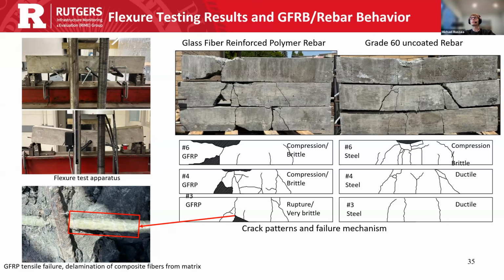And we can compare this to steel, where an over-reinforced section crushes at the top, as you know, in the compression block zone. And when it's balanced reinforcement, like with the number 4, or under-reinforced with the 3, we see a very prolonged ductile failure where the load gradually decreases over time as opposed to an abrupt failure event. And we can also see an example of the rupture. It's a more sudden decrease in strength capacity. And in this case, it seems to be a delamination of the composite fibers from the matrix in the bottom left image.